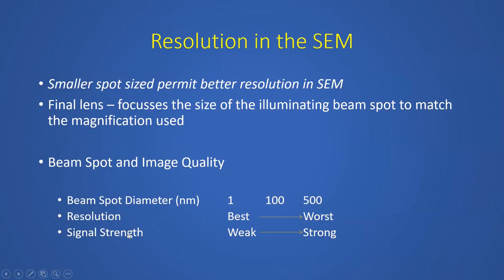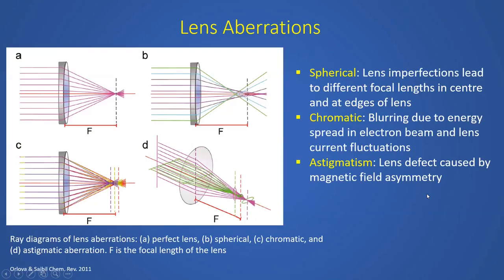Resolution in the SEM depends totally on the spot size. So the smaller the spot size, the better the resolution. Typically, the final lens is used for focusing the size of the illuminating beam spot to match the magnifications that are used. That's why it's the most important lens, the final lens or the condenser lens 3. This is responsible for the final spot size that you get at the specimen level. You can see here the spot diameter: 1 nanometer, 100 nanometer, 500 nanometer. As the spot size increases, the resolution decreases. This goes from best to worst, and signal from weak to strong. You get stronger signal but bad resolution, so you have to play around with the parameters to get the best results. But the important thing is that the spot size will determine the resolution of the SEM.